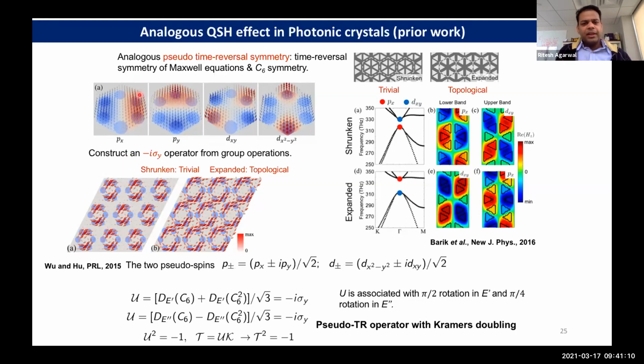And this is basically the H field, the out-of-plane H field. So one can create these orbitals, like this is the p-type equivalent orbital or the d-type equivalent orbitals. And then if you have a honeycomb, you have a Dirac crossing. But if you expand or contract the lattice while keeping the same hexagonal C6 symmetry, you break the C3 symmetry, so you gap out the system.